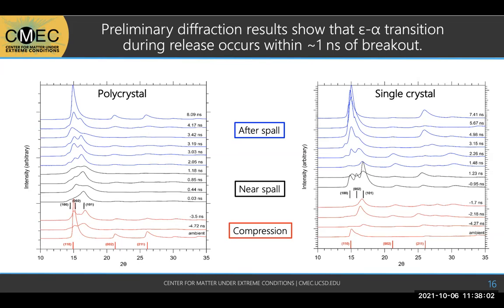When we look at these compilation graphs, and these are still pretty preliminary analysis, I need to go back and really thoroughly look at the diffraction patterns, but we can see that during compression we have that BCC to HCP change. And then at those really small positive values, 0.03 nanoseconds, 0.44 nanoseconds, or something like that, we see a BCC peak start forming pretty quickly. That was a really cool result, and I'm writing a paper on that now.